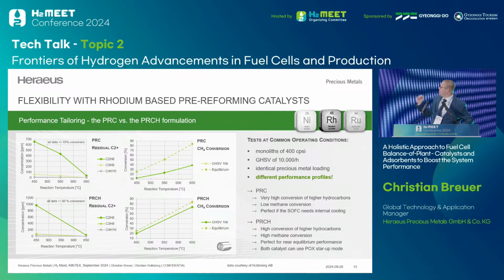And here is a very nice study we did on these materials, where we have to consider that the two types we show here, the PRC and the PRCH, have the same precious metal loading, but differ very much in their activity towards methane reforming. So we can pick a material that supplies the stack with either a methane-rich or a less methane-rich gas, while nonetheless very efficiently getting rid of the higher hydrocarbons, which is the main target of the pre-reformer. And this is a very nice example of how, with the materials we supply, we can tailor them to specific properties.